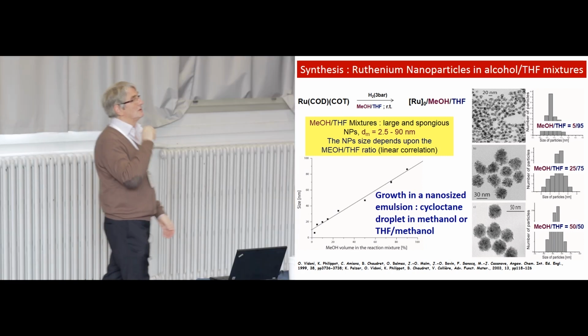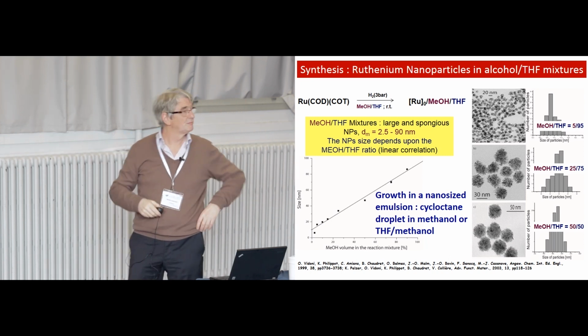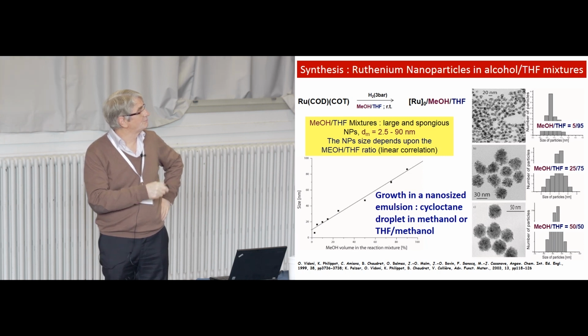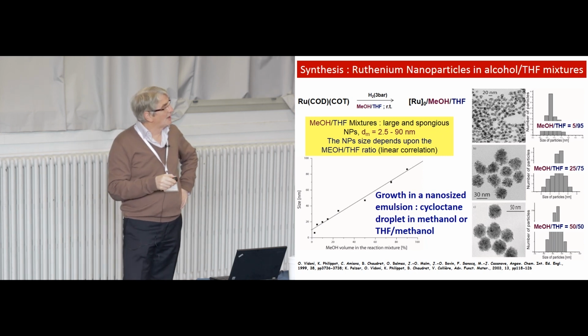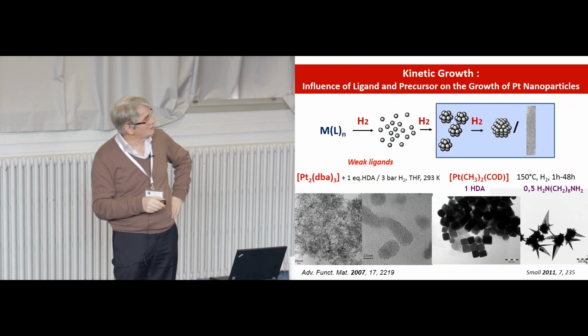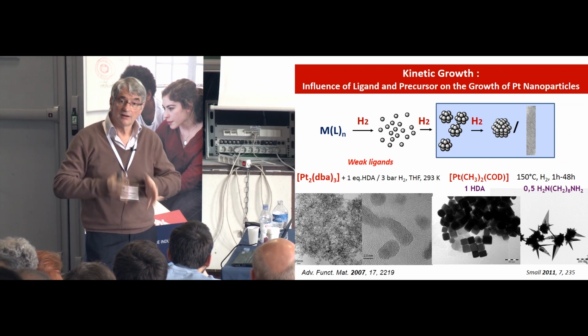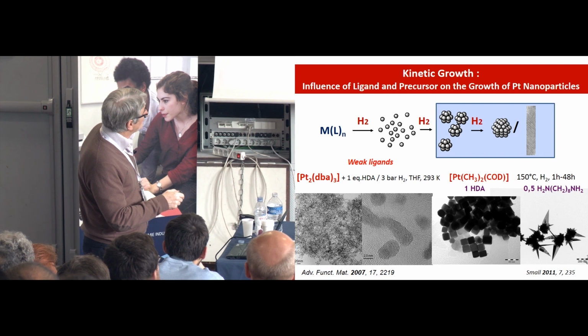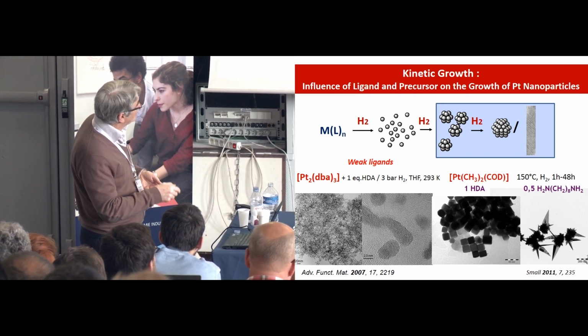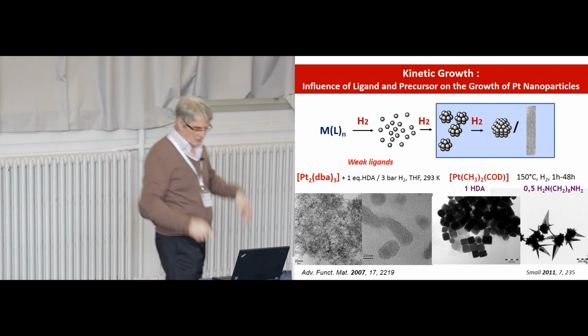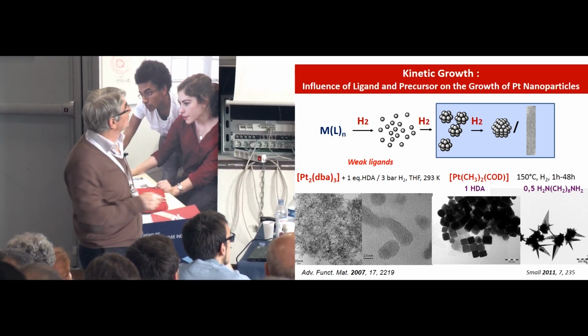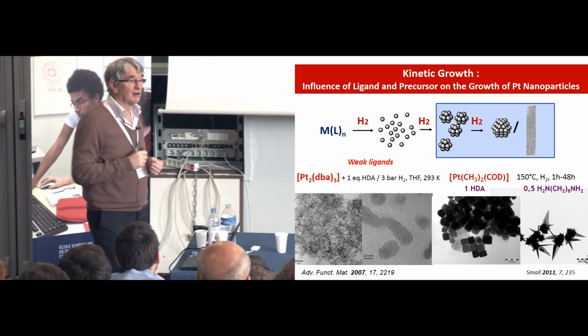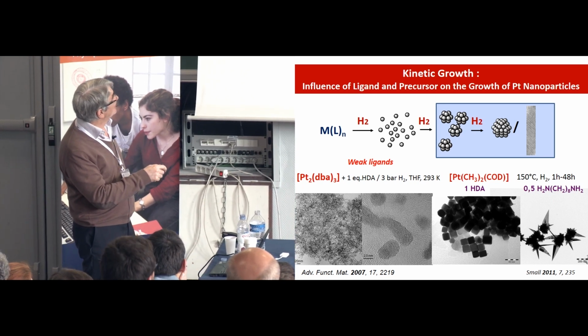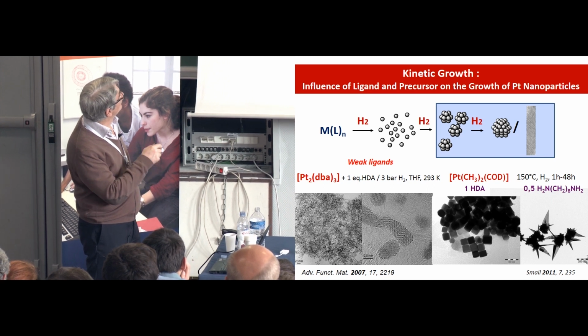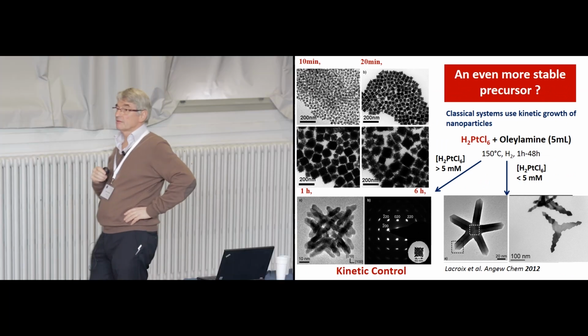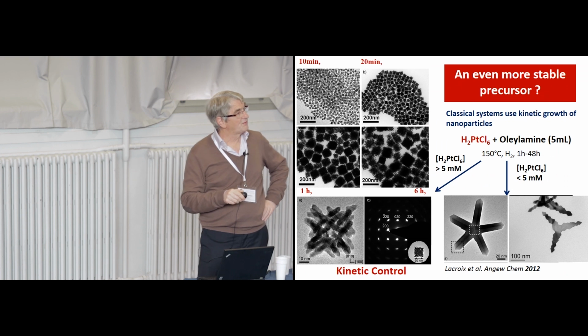We tried to look at how we could grow particles from precursors. For example, we used platinum DBA on an olefin complex, and we could see that starting from small particles, we could make spaghettis by using HDA which would direct the coalescence of the particles. With a precursor which decomposes with more difficulty, in the presence of amine or diamine, we could grow bigger structures. But the real surprise came when we took platinic acid as a precursor, which is not really organometallic, and then in the presence of oleylamine, depending on the concentration, we could get either single crystals, dendritic nanoparticles, or five-fold and three-fold stars.